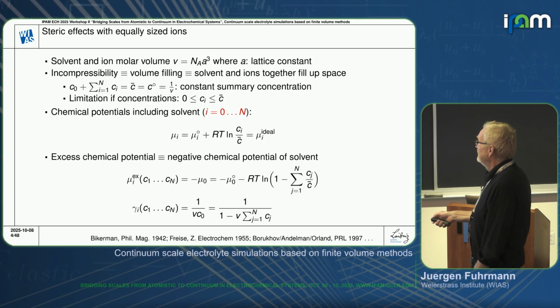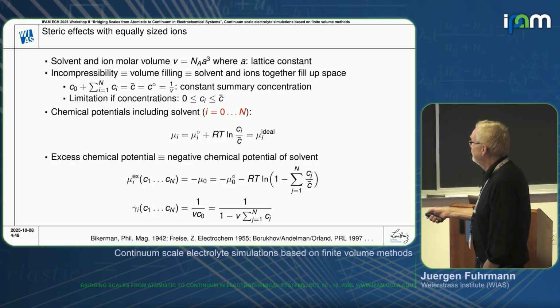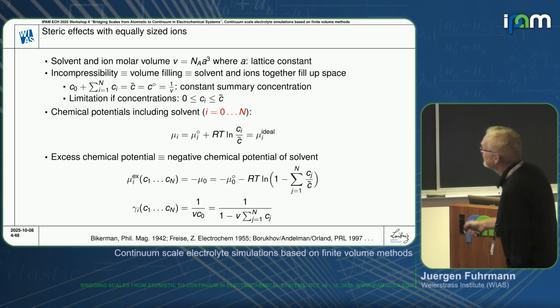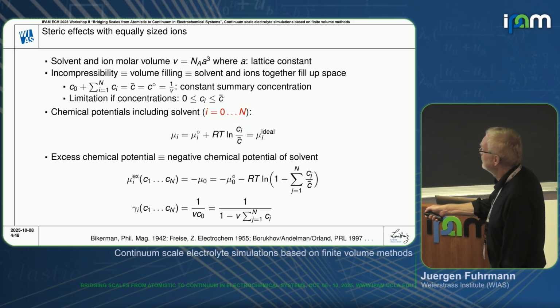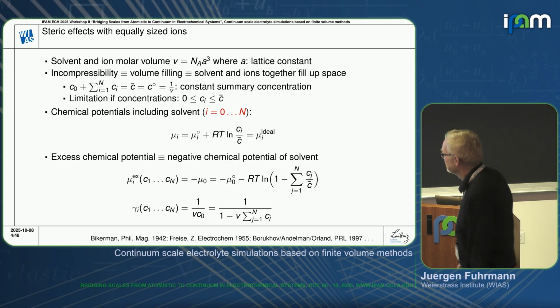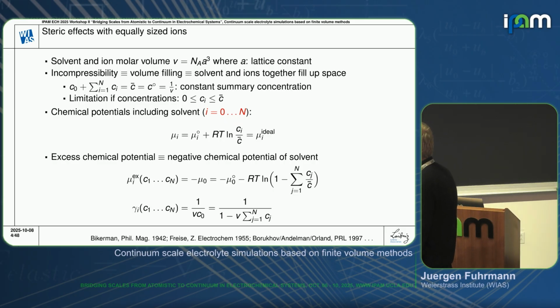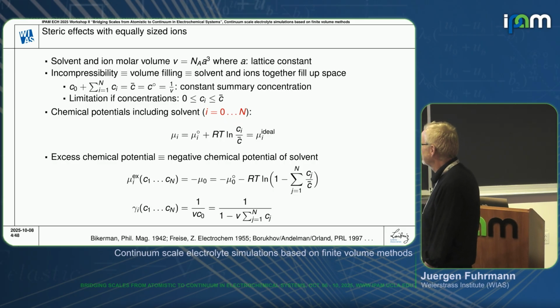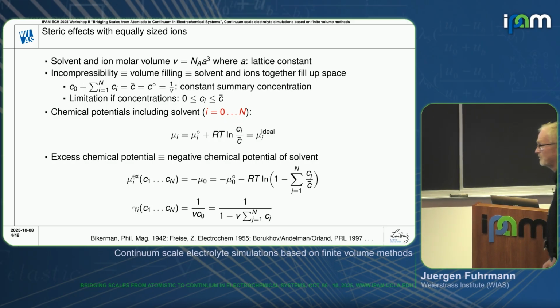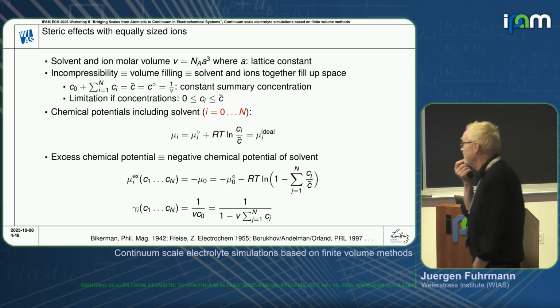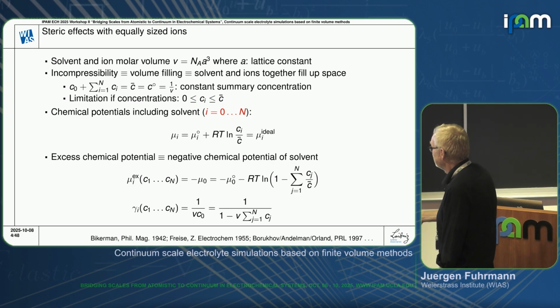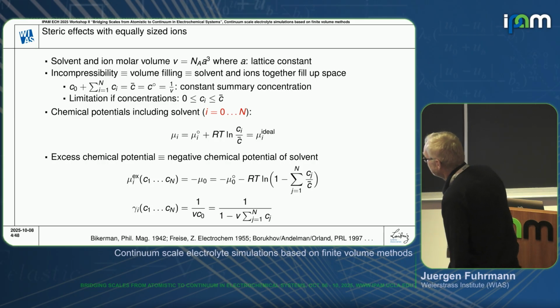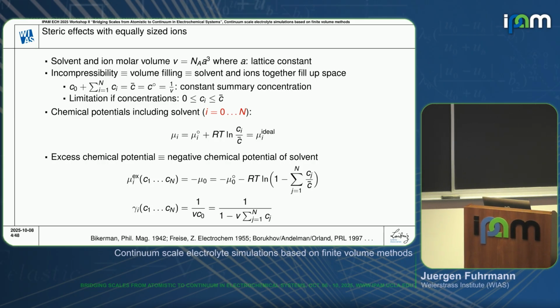And then we can introduce the ideal gas chemical potentials for all species, including the solvent, and calculate the solvent concentration from the incompressibility constraint. And we assume that the excess chemical potential is just the negative chemical potential of the solvent, which then depends on all the other species in this kind of term, and this is the equivalent activity coefficient here.